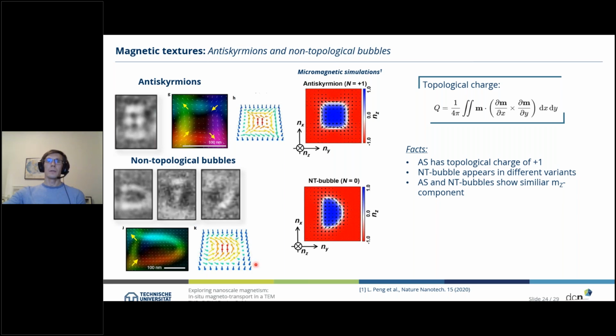And if we use micromagnetic simulations again, we can simulate the structures of an anti-skyrmion and a non-topological bubble. And what is plotted here is the Z component, color-coded from -1 to 1, of the magnetization, and then the arrows point the direction of the magnetization. And this for the anti-skyrmion and non-topological bubble. So what can we learn from that micromagnetic simulation?